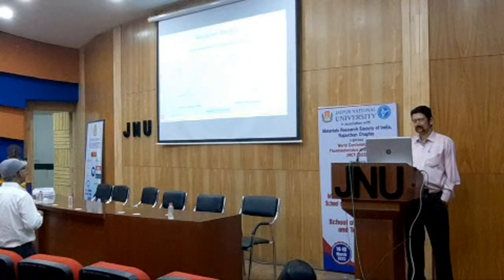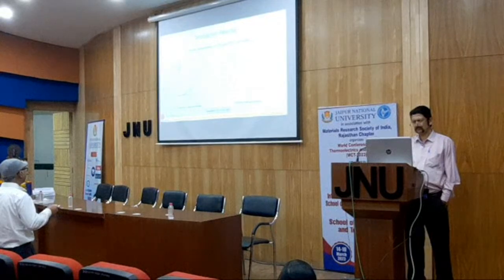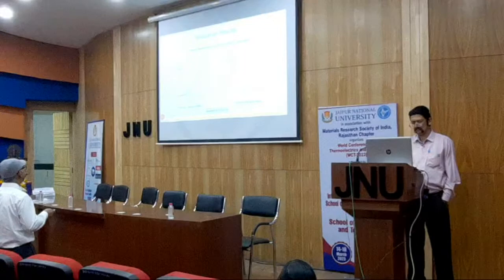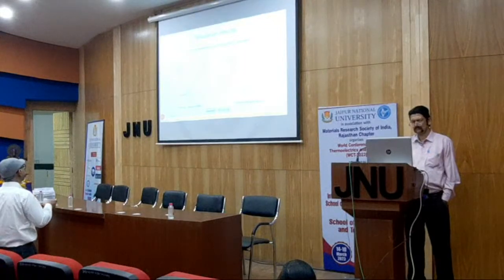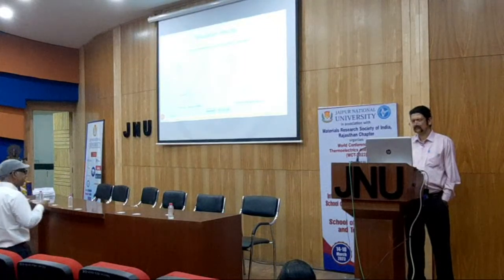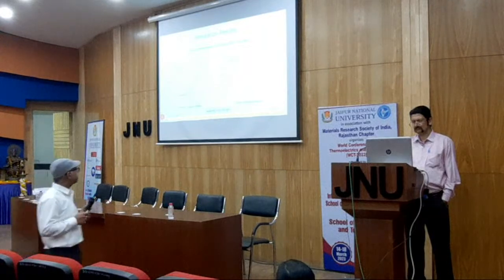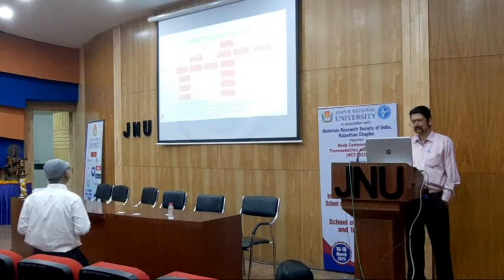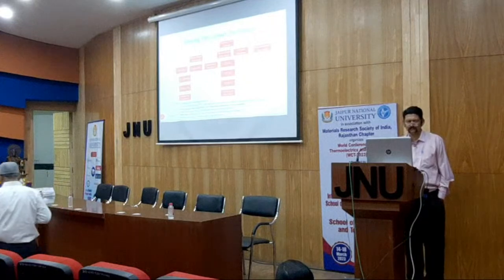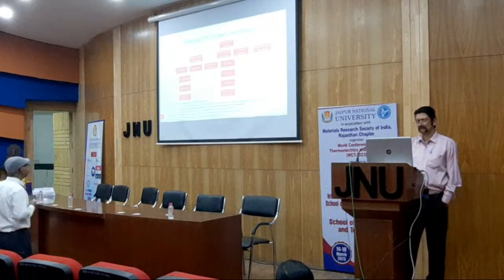From this we have taken the transfer characteristic and output characteristic, and from these the sensitivity is found to be 59.3 millivolt per pH. This is the case for titanium nitride based EG-FET. For the same materials we have also developed the EG-FET. Next please. The titanium nitride film which I am discussing,